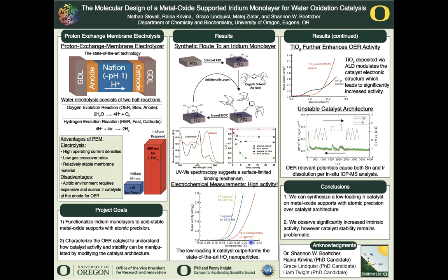So we see that the low loading iridium catalyst actually outperforms what was previously thought of as the state-of-the-art iridium oxide nanoparticle catalyst. And then we got greedy. We said, can we make it more active? Can we further tune the electronic structure of our catalyst and increase the activity? And we could, we could add TiO2 to our catalyst, and we see that it increases the activity even more. And interestingly, that doesn't make it any less stable, which kind of breaks this activity stability inverse relationship that people will often see in the literature.